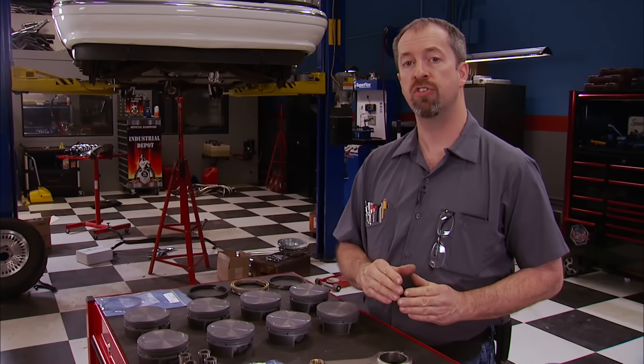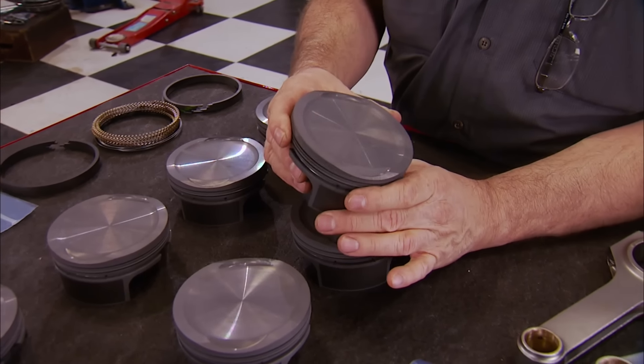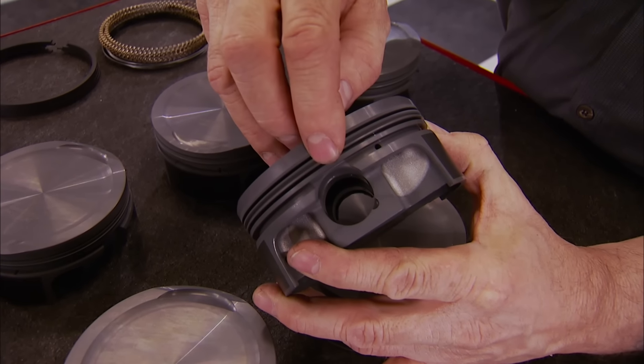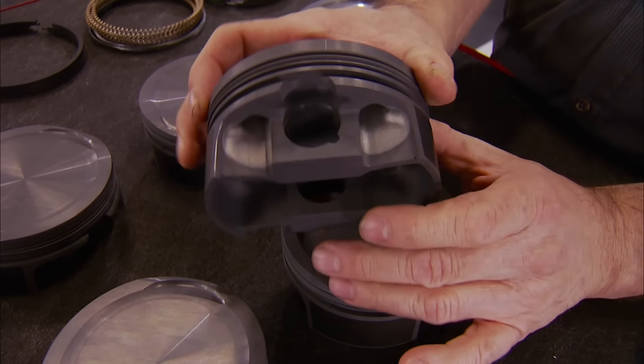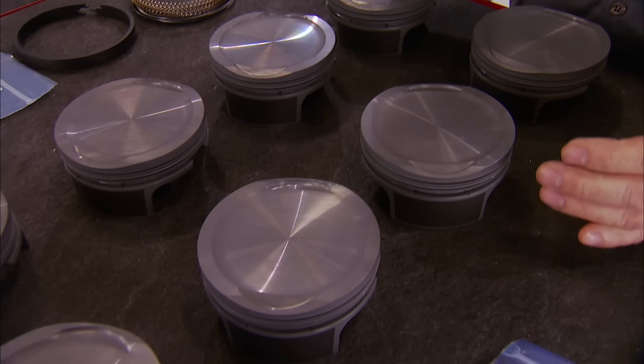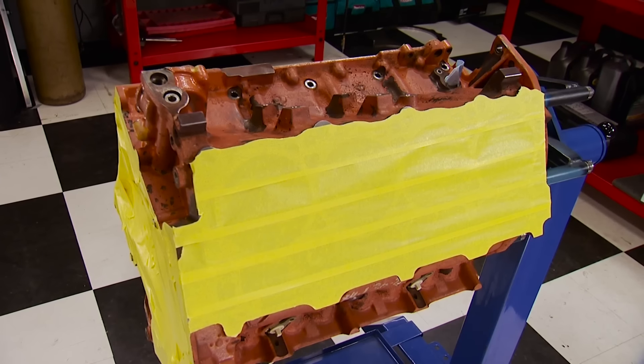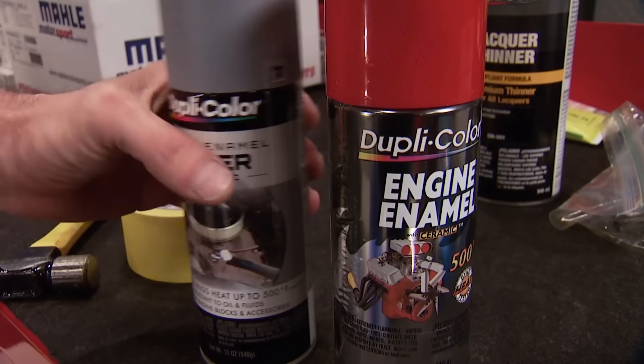Mahle Motorsport never disappoints when it comes to piston quality. These are forged from super tough 4032 low-expansion aluminum alloy with a CNC'd inverted dome and dual valve reliefs. They have ultra-flat 1.5, 1.5, 3 millimeter ring lands, set up at a 1.095-inch compression height to work with our 4.050-inch stroke crank. They accept a .927-inch wrist pin — standard small block Chevy size — with a phosphate coating and proprietary anti-friction coating on the skirt.